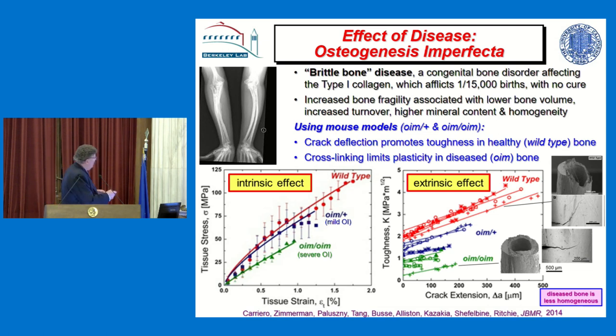If you look at the extrinsic mechanism, this is the R curve, toughness versus crack extension. The red is healthy bone, and the bone breaks. These are mouse bones, by the way, and they break at 45 degrees because the crack hits those osteons and deflects along that direction. They're not osteons in mouse bone, but they're mineralized regions. But if you look at the diseased bone, the crack doesn't deflect. It just goes right through. So you've lost that mechanism.